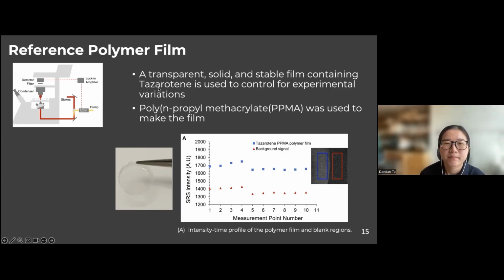So this polymer film can track this signal fluctuation, and then later when we measure the signal from topical drug applied to skin, we will normalize the topical drug's signal to the standard signal, so that in this normalization process we can remove this effect and only keep the signal that is related to the drug permeation.